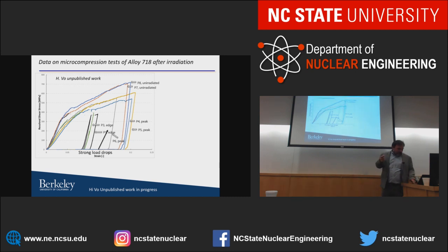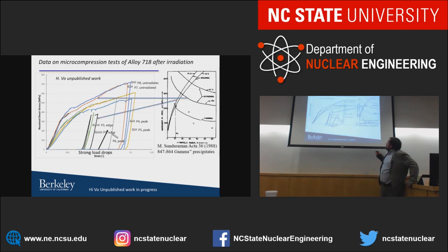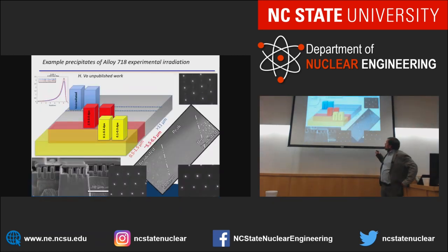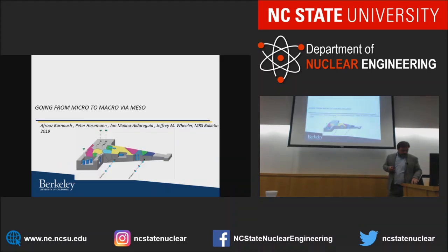Why is that? Well, if we dissolve them only a little bit, the precipitates become smaller, and we are in the cutting regime of our dislocation. The dislocation is able to cut through it. If they're too large, it will loop around it. And if we don't have any precipitates, well, then there's no resistance anyway, and then it won't cut or loop, and will simply deform homogeneously through our material. So by observing our stress strain curve and understanding our microstructure, we can see when our particles dissolve and when they don't dissolve due to radiation in the material. All right.